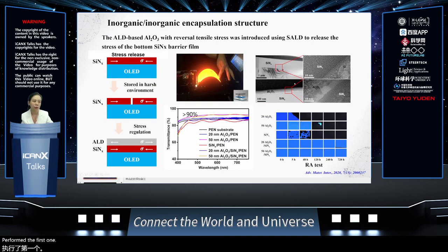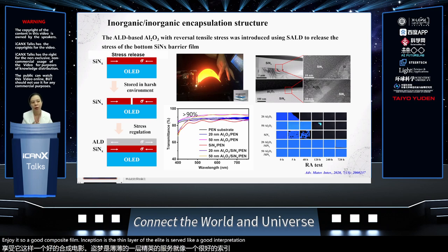The first one is ALD composite layers with industrial PECVD silicon nitride. Without these ALD processes, the OLED structures deteriorate quickly through water. With only ALD, sometimes you get good performance, but many times you get failures because it's too thin and a small particle can completely destroy it. So a good composite film is a thin layer of ALD, which serves as good encapsulation, and then a PECVD nitride, and these two layers help minimize the stress levels.